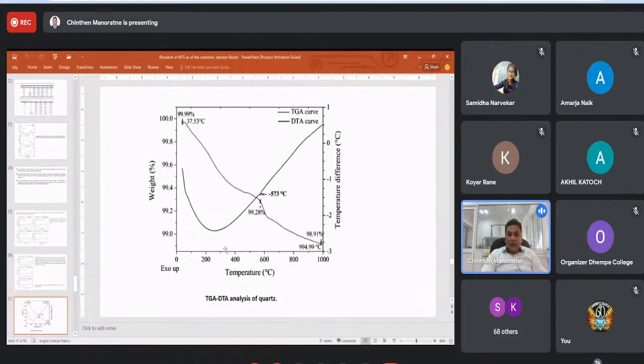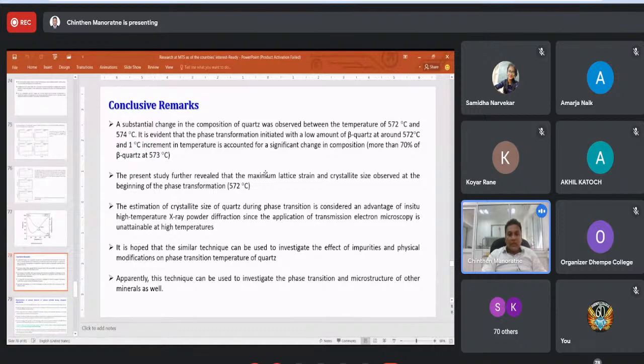And this is the thermographic analysis of quartz. You can see at about 573 the conversion. And in the concluding remarks, as I mentioned, a substantial change in the composition of quartz was observed between the temperatures 572 to 574. It is evident that the phase transformation initiated with a low amount of beta quartz at around 572, and a 1 degree centigrade increment in temperature accounts for a significant change in composition.